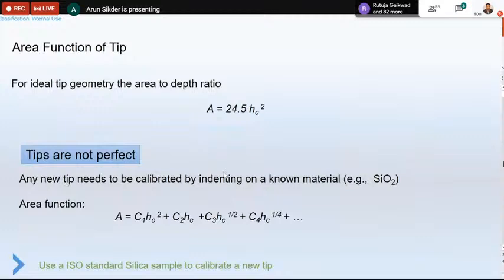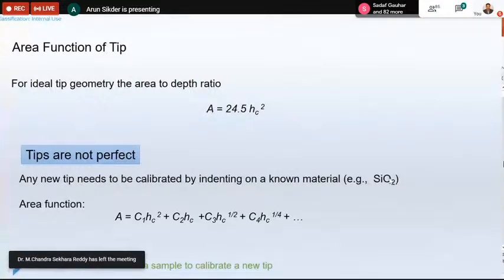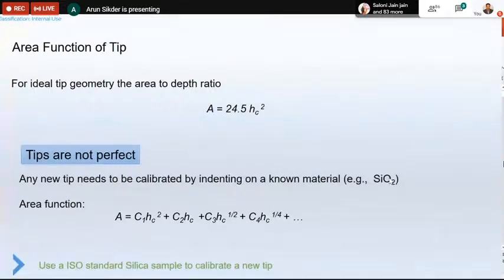We use a known material, SiO2, which is a quartz single crystal, and we know its mechanical properties very accurately by other means. That is a standard sample available, an ISO standard sample. We can measure its properties, and knowing the known property, I can recalibrate my tip area function. Instead of only a single value, I can take several different values and then put it in my software to take care of it.